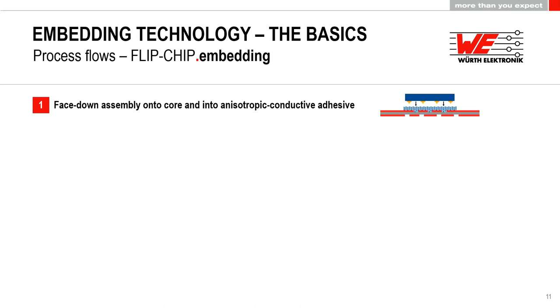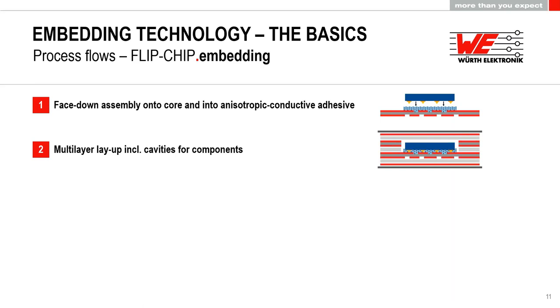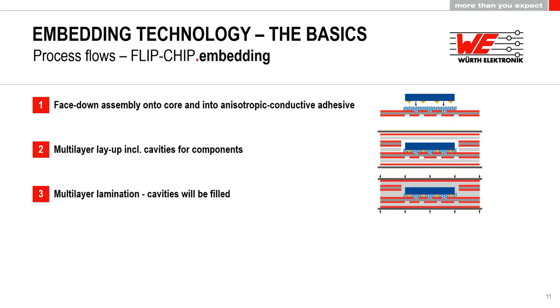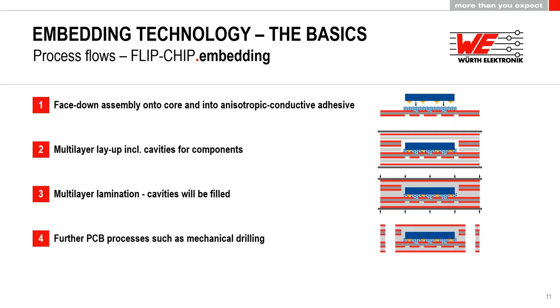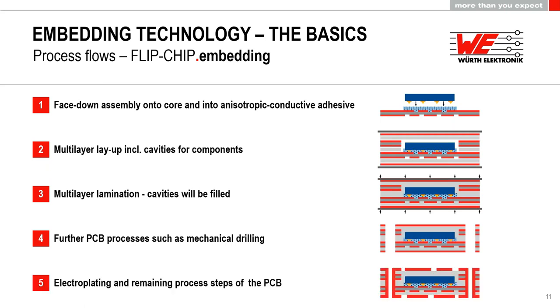The glue will be hardened in that assembly process instantly so that the component is electrically and mechanically fixed onto this core. The remaining steps are basically almost the same as for the other technologies. We go to the layup, we create this cavity, we put it into the pressing system, the resin starts to flow, is pressed into the cavity and starts to flow around the component. And then we have the remaining PCB processes like mechanical drilling, outer layer structuring, solder resist, and so on to create the final PCB.